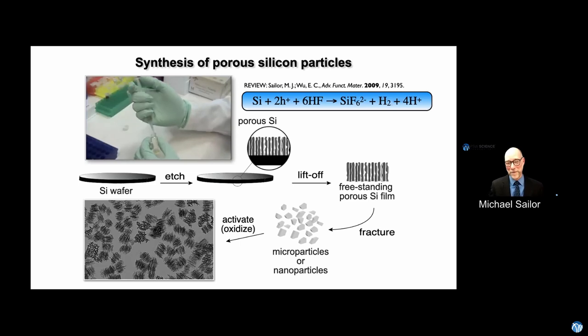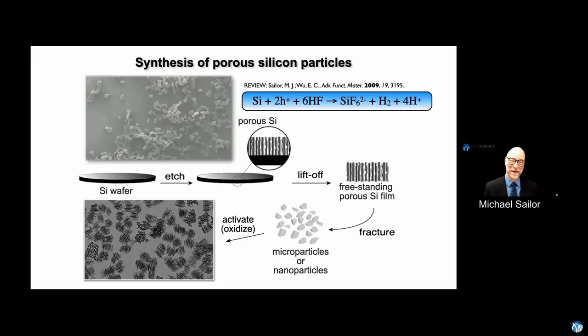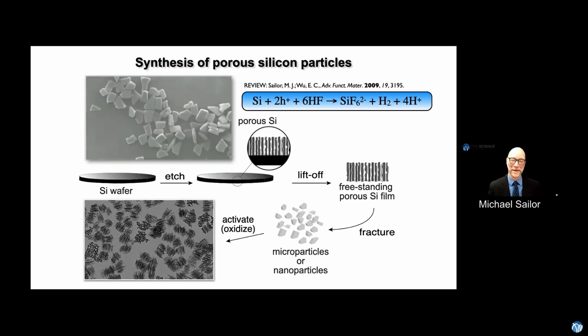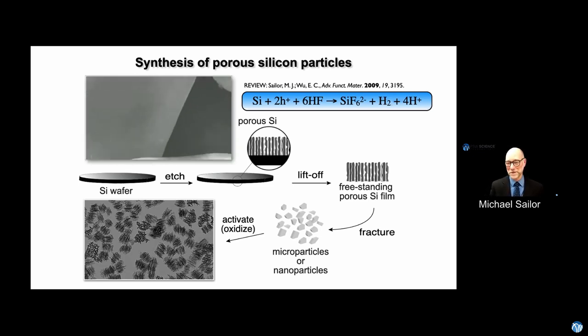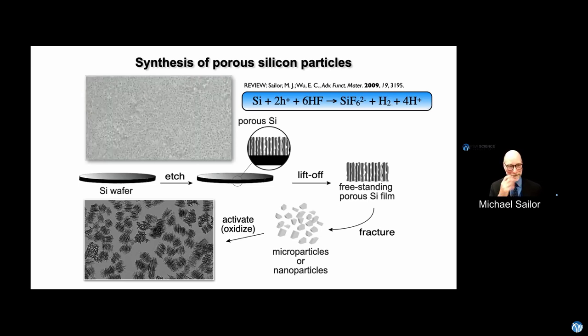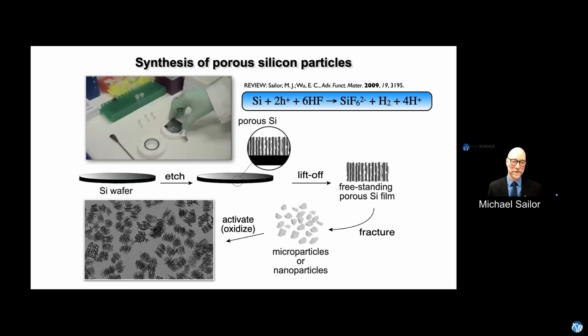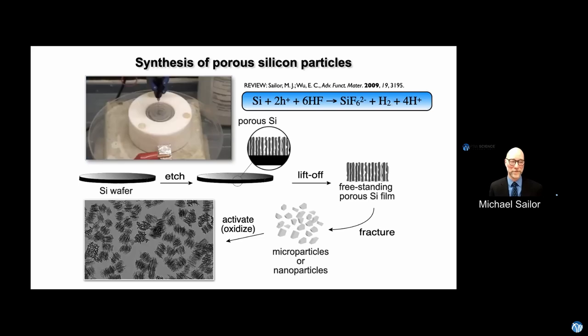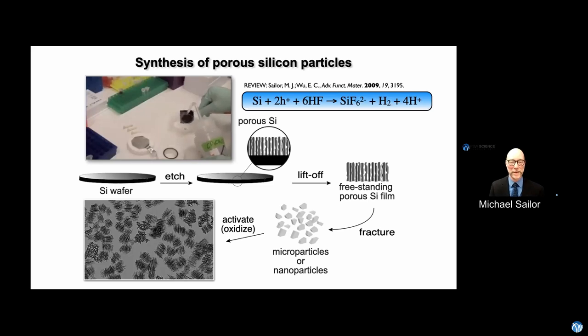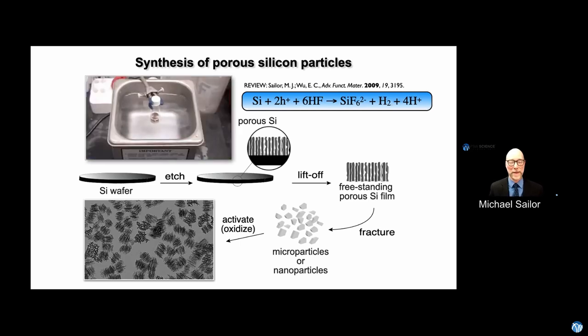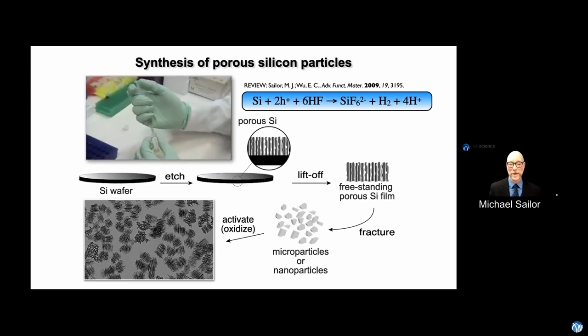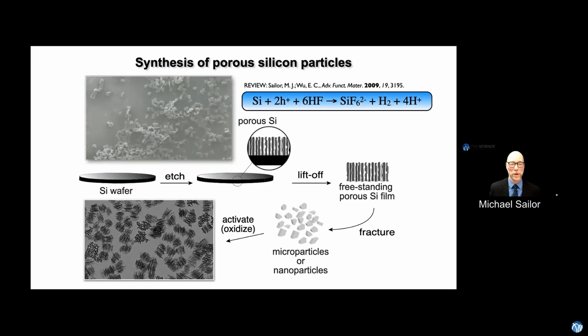We start our experiments every day with silicon wafers, and we make silicon-based nanomaterials by an electrochemical etching process. This movie is going to play again in a loop. First, we put our wafers into a little Teflon-based etching cell. We fill that cell with hydrofluoric acid and run electric current through it. That electric current machines out very small channels, nanometer-scale pores in the material, which is why we call it porous silicon. The brown powder and films you see are the porous layers that have been pulled off the wafer, broken up in an ultrasonic bath, and made into small nanoparticles.